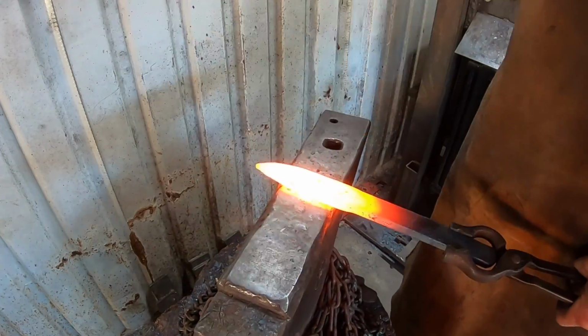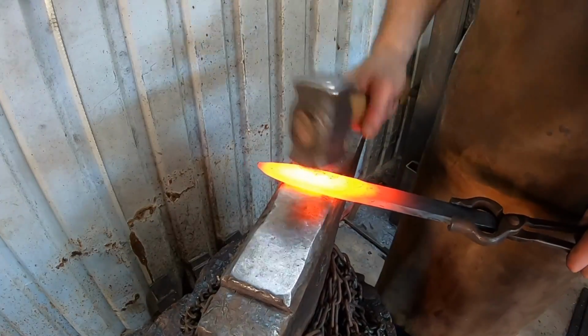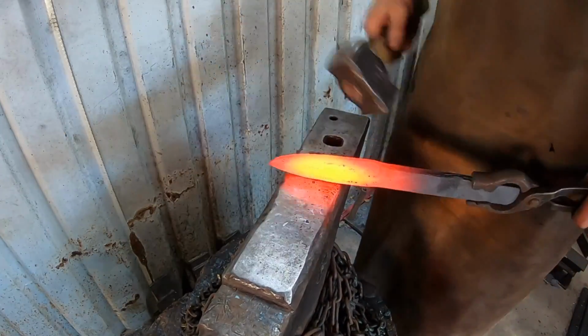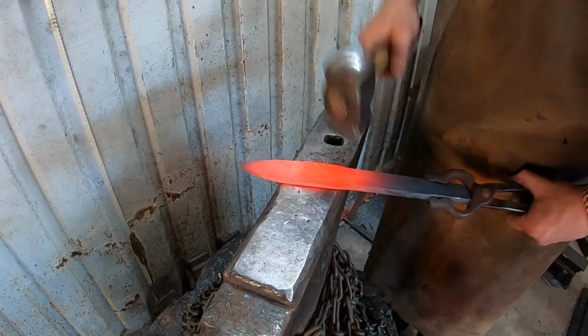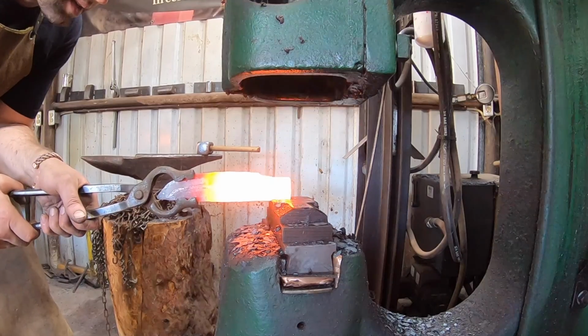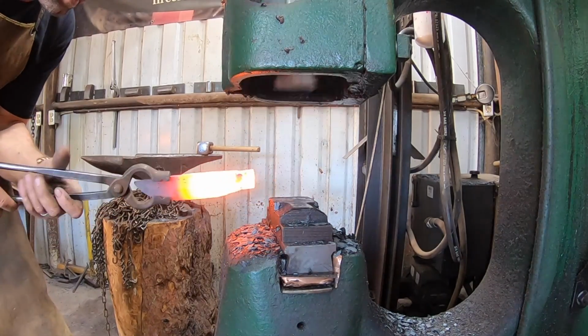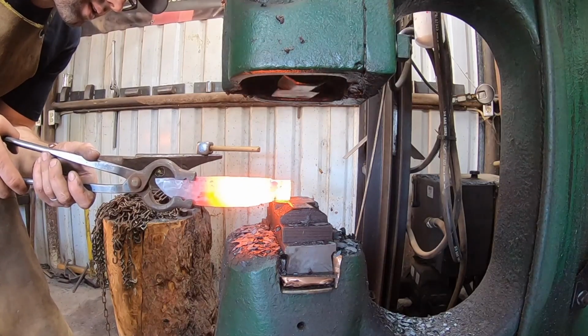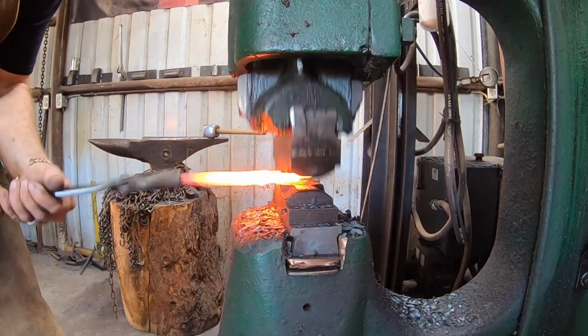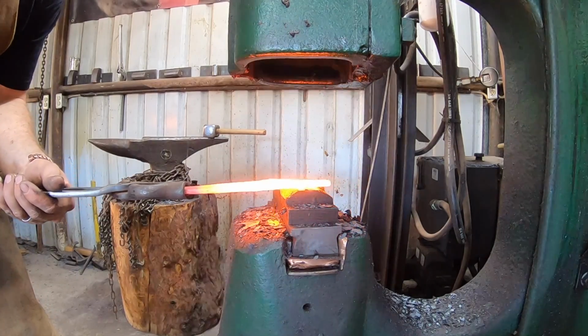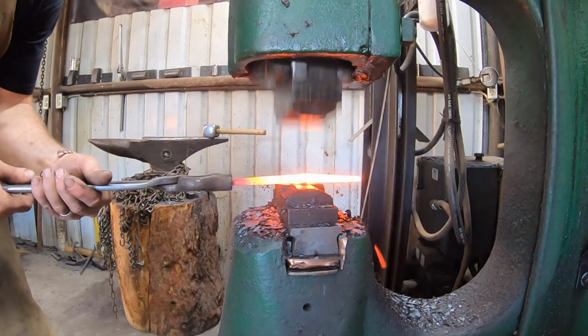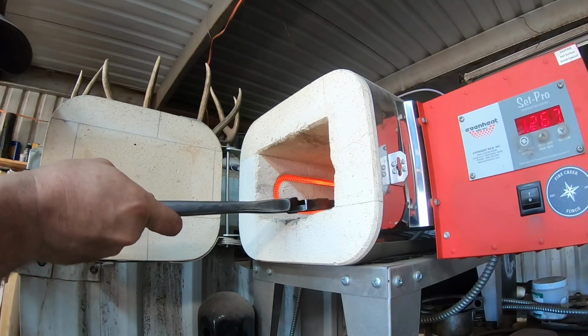Now this is not a sanmai, this is simply a composite blade, and one nice thing about doing it this way is that when one half or one side of the blade is edge steel and then the top half or top side is your patterned and tough steel, you don't have to worry about keeping things perfectly centered as you do with a sanmai, because that edge steel is all the way across on the thickness of the blade.